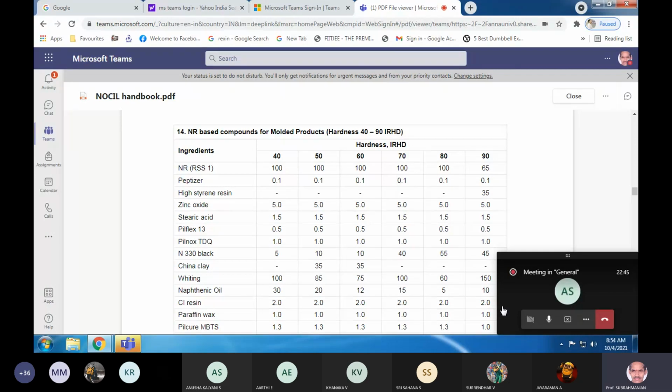So with the oil and the whiting, what is it that I use? And the calcium carbonate, we said in one of the classes, it is a partitioning agent, anti-tack, right? So NR is known for its tackiness, and with the whiting, we are countering its tackiness. So that is not appropriate. Therefore, I add a tackifying resin, CI resin. CI resin, Coumarone Indene resin. Make a note.